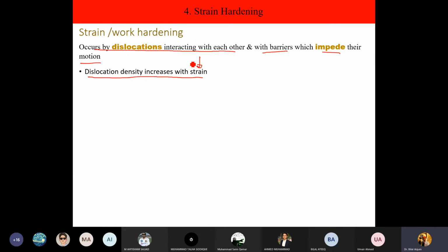So if we look at the dislocation density formula, it is basically the total length of dislocation divided by the unit volume in which that dislocation length exists. And it is being further explained that for an annealed sample, which is a stress-free, soft, ductile sample, the dislocation density is about 10^5 or 10^6 centimeter per centimeter cube of the material.